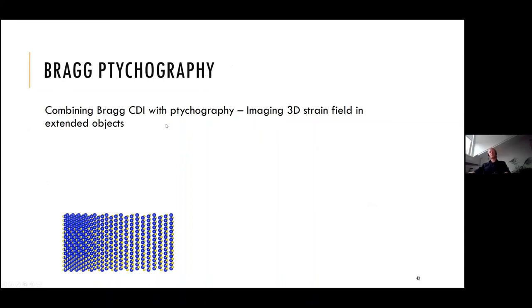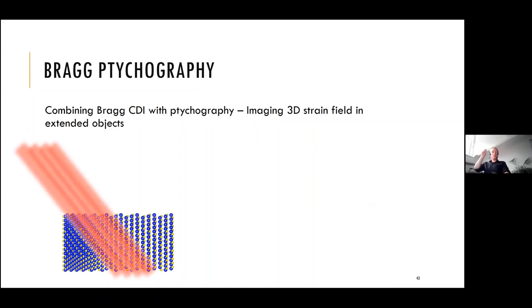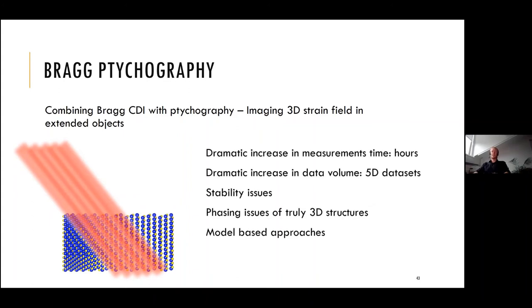So if you want to study the three-dimensional strain distribution inside extended objects, you basically combine the Bragg CDI approach with the scanning technique, where you go with your focused beam through the extended object and collect a diffraction pattern from each position. I briefly want to mention the major differences to Bragg CDI. It's basically the dramatic increase in the measurement time, which can be hours depending on your sample and the amount of signal you can record.